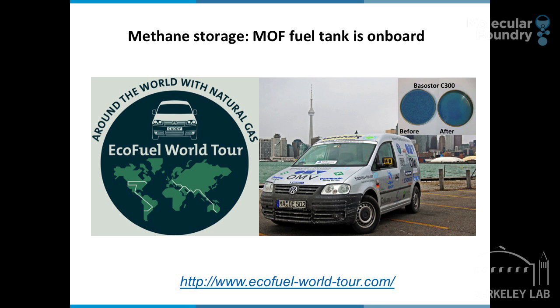In this particular demonstration of the usefulness of MOFs, this Volkswagen automobile was equipped with a MOF tank and driven around the world 28,000 kilometers with the fuel supplied from the various locales without pre-purification. This experiment was to demonstrate that the MOF can survive the journey with contaminants, whether they are small particles from the air or trace contaminants that might be in the natural gas supplied, such as sulfur contaminants and water. The material at the end of this exercise turns out to have lost only 10% of its porosity, a minute amount compared to the very large surface area that these MOFs have.